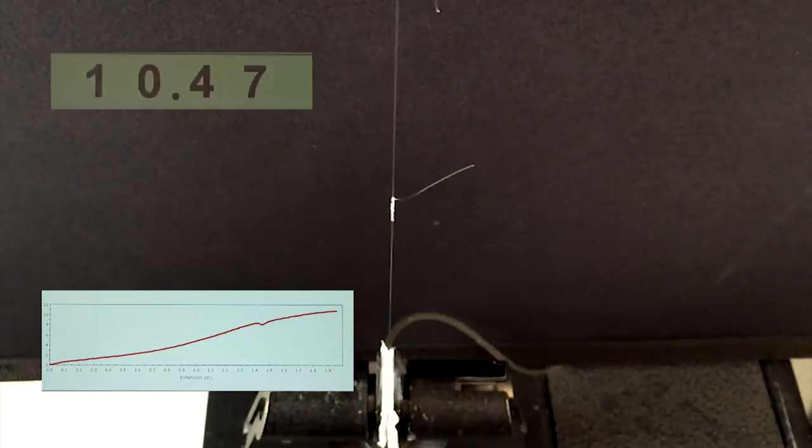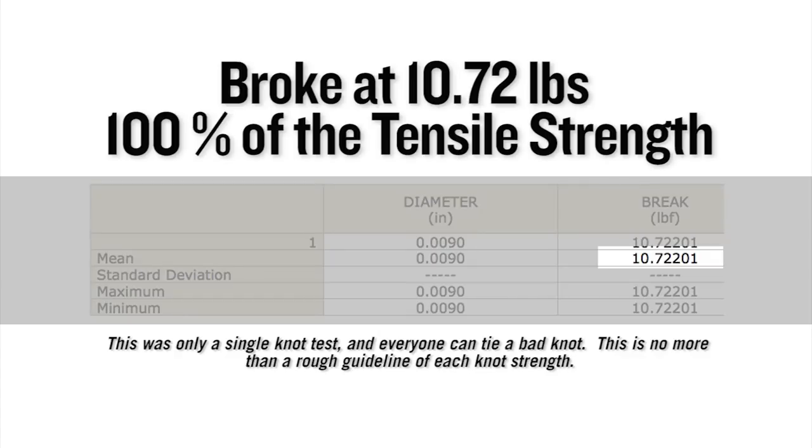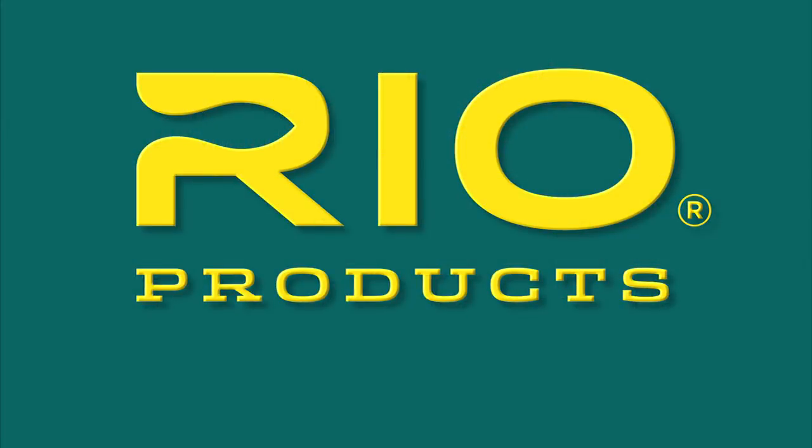On a single Instron test, this knot broke at 10.72 pounds, which equates to 100% of the tensile strength of the nylon it was tied in. Rio. Make the connection.